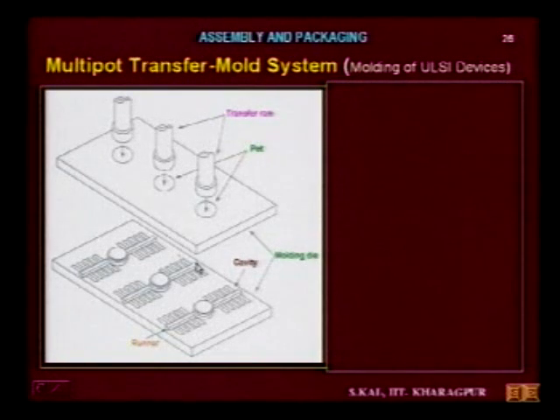The lead frame often has long, fragile fingers, and the chip is interconnected to these leads with 25 to 30 micron diameter gold wire. To avoid damaging this fragile structure, the viscosity and velocity of the molding compound must fall within a certain range. Commercially, molding compounds are designed to meet these requirements when molded at approximately 175 degrees centigrade and at a pressure of about 6 megapascal, where the upper and lower molding dies are pressed at about 18 megapascal to avoid resin flash.